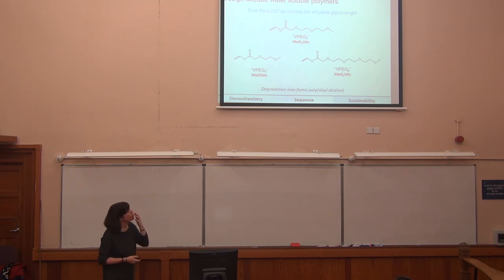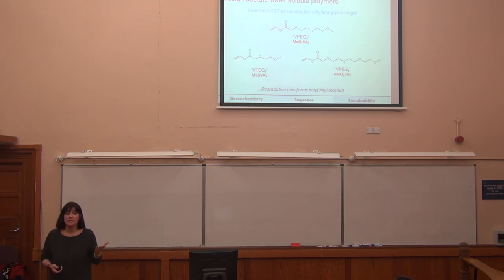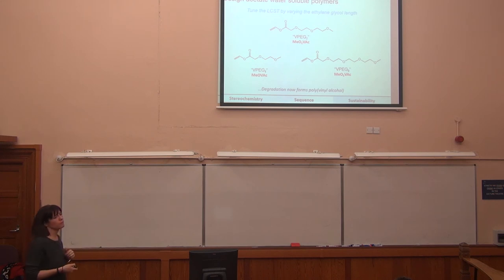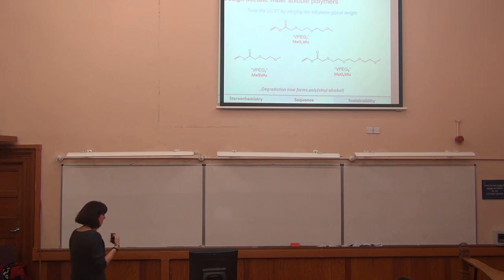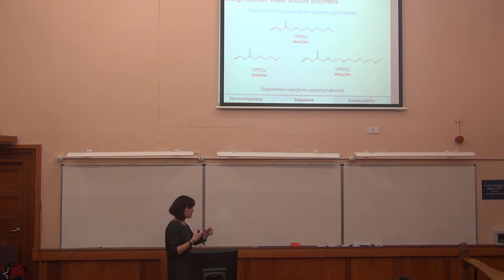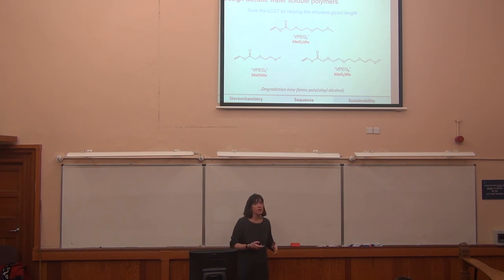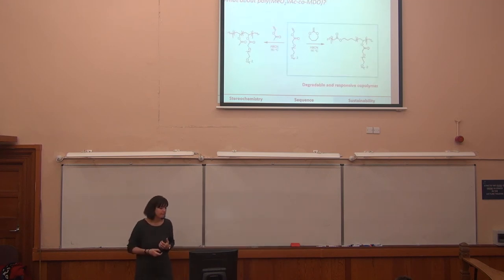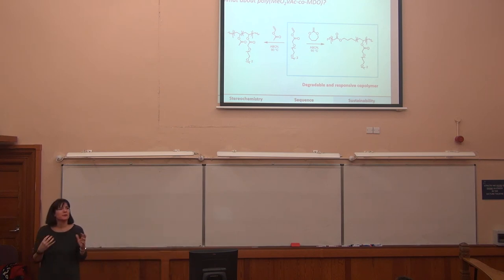And we made this family of polymers that look very similar, but they're actually vinyl acetate derivatives, so derivatives of polyvinyl alcohol. And so degradation will now form polyvinyl alcohol. And if we can mix these types of polymers with some of our MDO-type polymers, we can form degradable polyvinyl alcohols, degradable hydrophilic polymers for drug delivery. These co-polymerize very well. We've been able to match reactivity ratios. This was maybe a whole PhD's work. It's quite depressing when you put it on one slide.